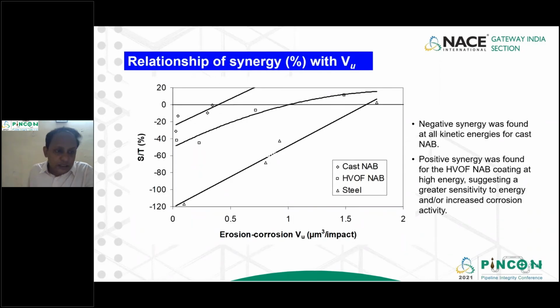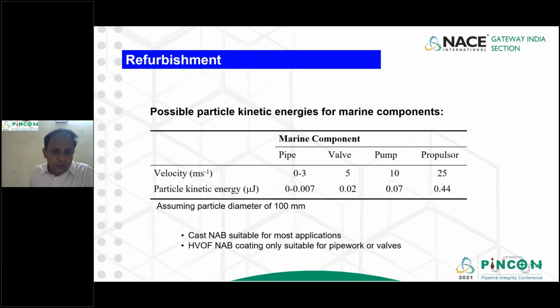We calculated the ratio of synergy to total, and here you can see a lot of materials at a certain erosion rate. If I look at the lowest kinetic energy in that study, all are negative values. But as the impact increases, the synergy goes to the positive side. That indicates the material is very sensitive to impact and increases the corrosion rate.